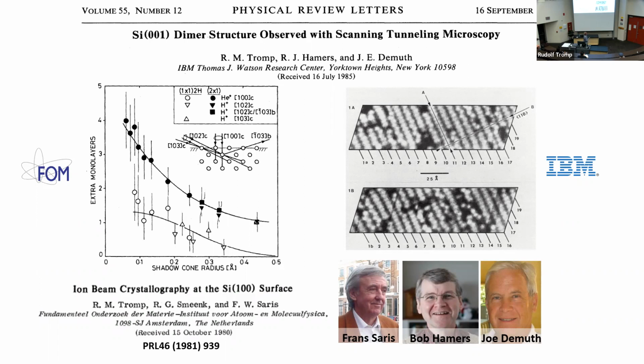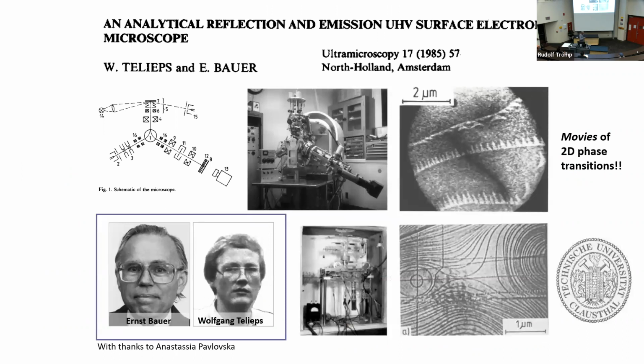So this was, you see the date here, 1985. In that same year, Ernst Bauer, in the back of the audience here, and Wolfgang Telieps published this paper in Ultramicroscopy, also 1985, analytical reflection emission UHV surface electron microscopy, where they show that if you bounce electrons from a surface at very low energy, a few eV, and you use the reflected electrons to form an image, you can see atomic steps on the surface. And I heard Ernst give a talk probably 2 or 3 years after this, where he